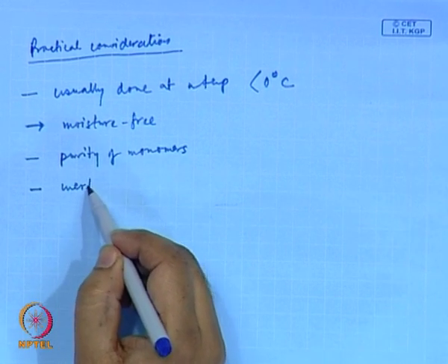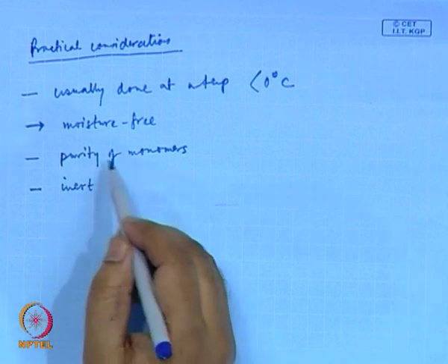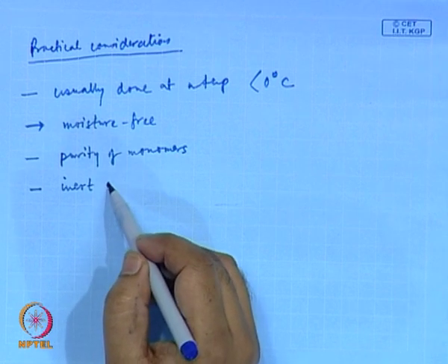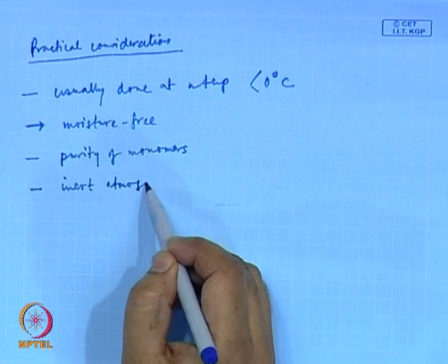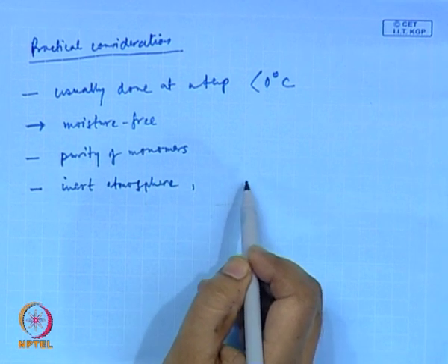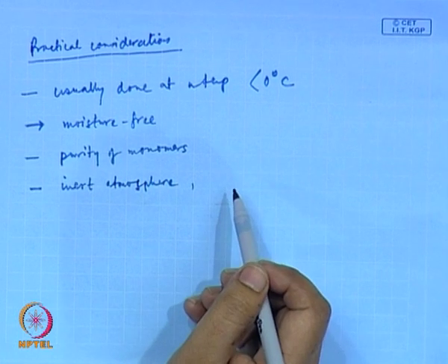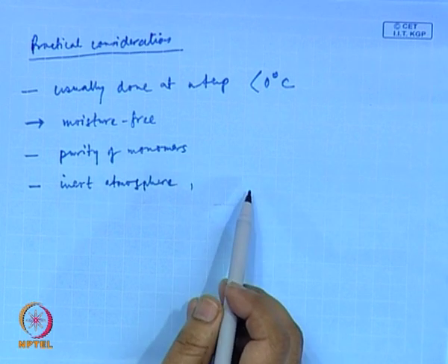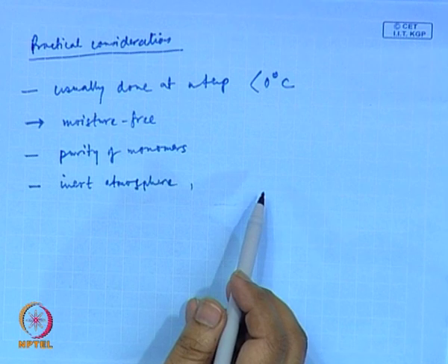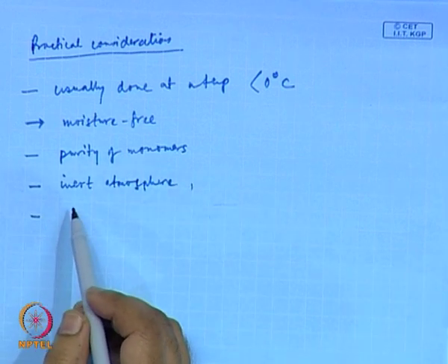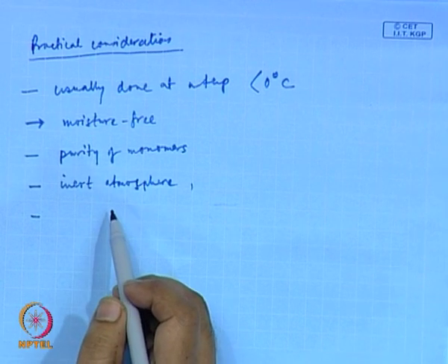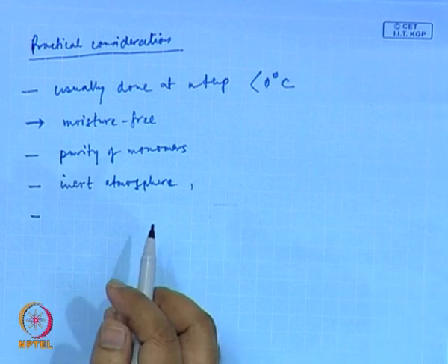Oxygen is also a killer for this cationic polymerization, so an inert atmosphere is needed, and for that the nitrogen or the argon gas which are used for creating the inert atmosphere must be purified very rigorously. And because these reactions are very fast, sometimes happening in seconds, the cationic chain reactions need an arrangement to be able to perform the reaction.